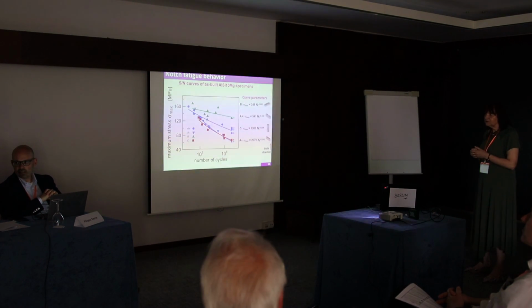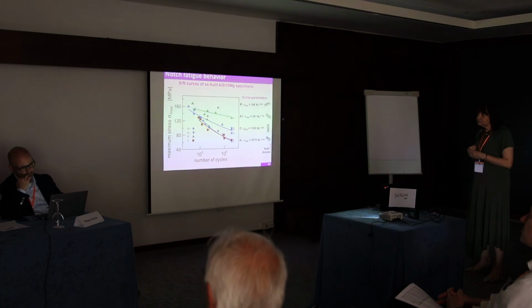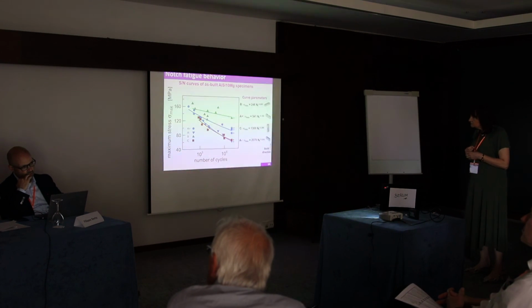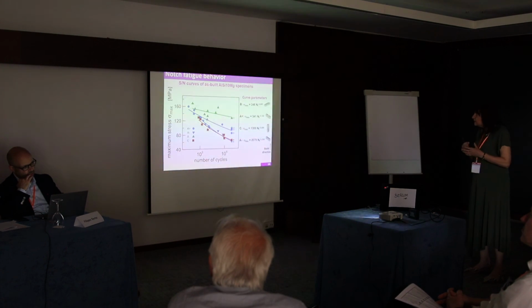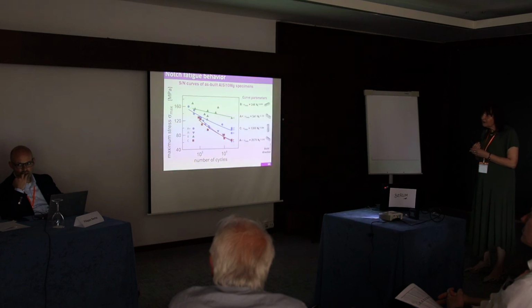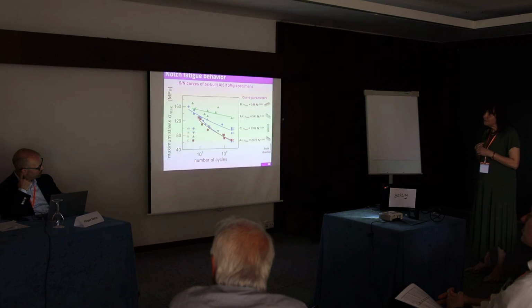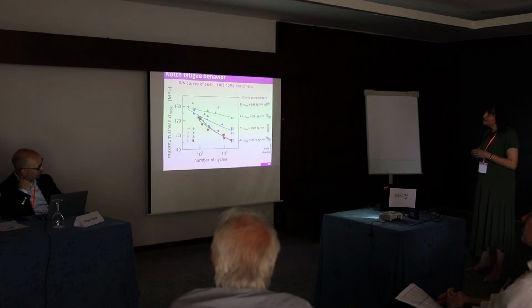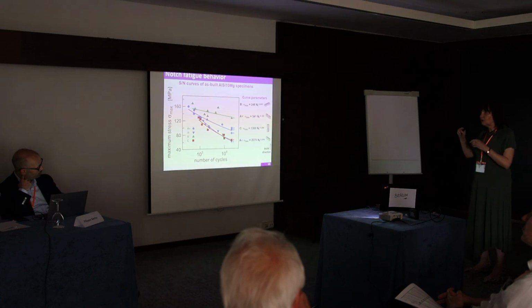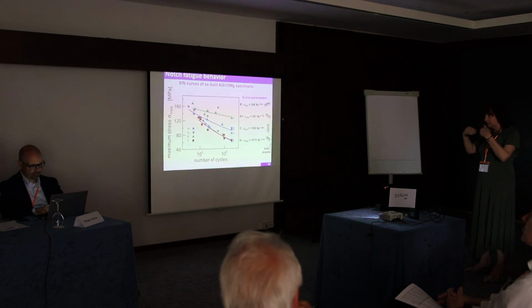Yes, clearly, but the issue is that the scatter is a lot higher than the other one. I agree, so it would be good to check probably the fracture surface, to see if there has been any possible defect. But we studied, but only on the flat specimens, not in the notch. So this we have to do.